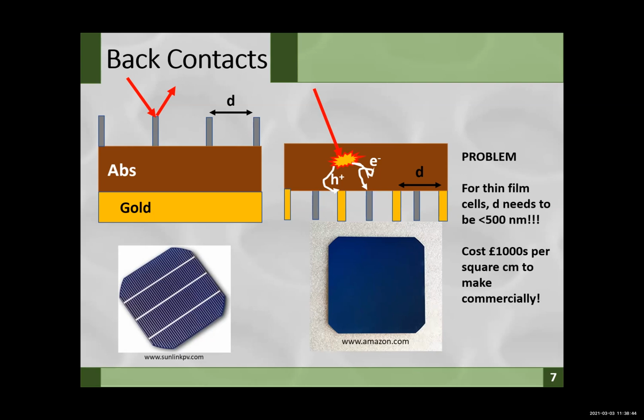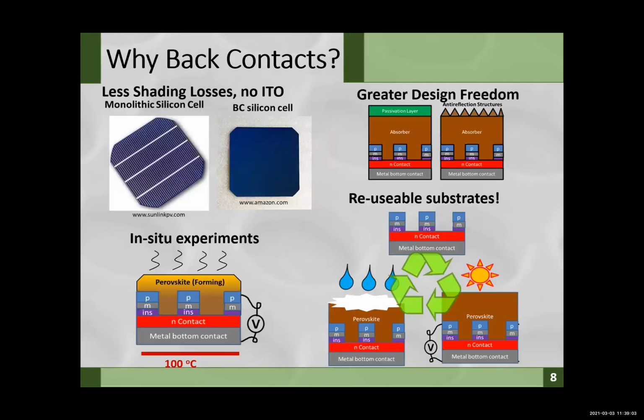However, for thin film solar cells, there's a catch in that the separation of these contacts needs to be a lot smaller, like 500 nanometers, which is about the size of a coronavirus. And it costs you in the thousands of pounds per square centimeter to make something like that commercially, if you're doing it for a thin film solar cell.